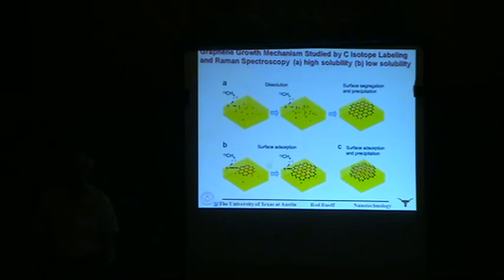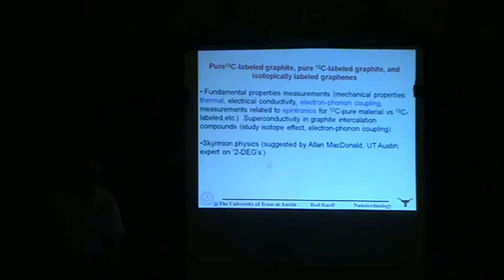Both are being studied. Particularly if we want to make multi-layer graphene, we're going to use copper that favors monolayer growth. We're going to have to invent different parameter spaces to try to grow the next additional layers. Maybe switch the precursor from very stable methane to something that's very unstable like acetylene and so on. But if we're going to try to grow multi-layer by precipitation, we have these choices. And we might, by kinetic control, quench even with the thick nickel piece where we might have saturated the carbon, so most of the carbon will stay in the nickel and we end up with a thin layer of graphite.